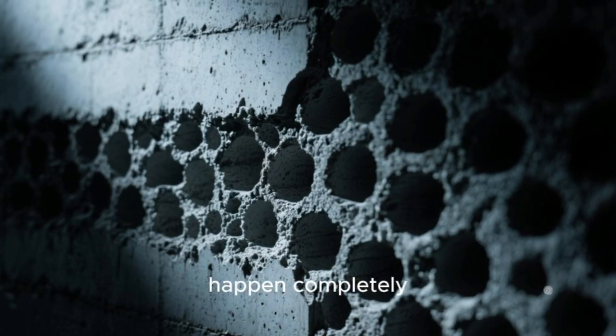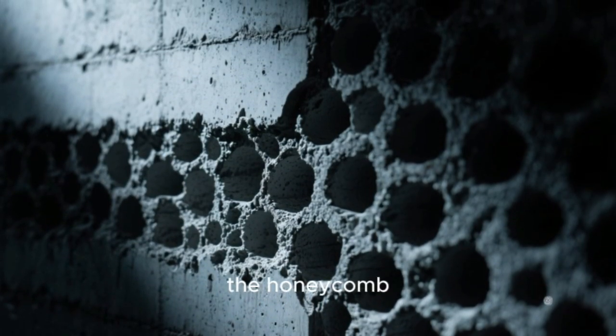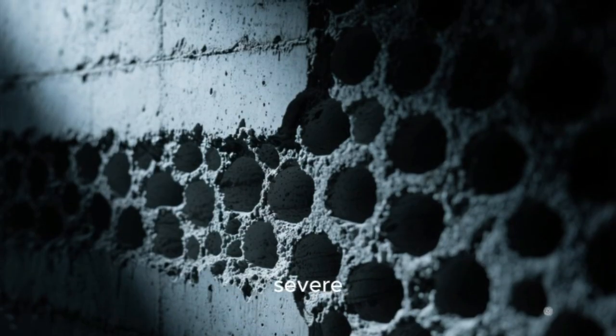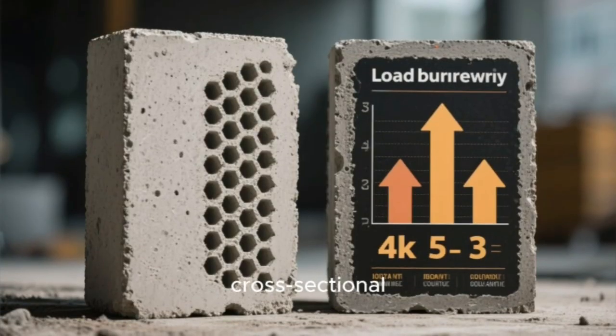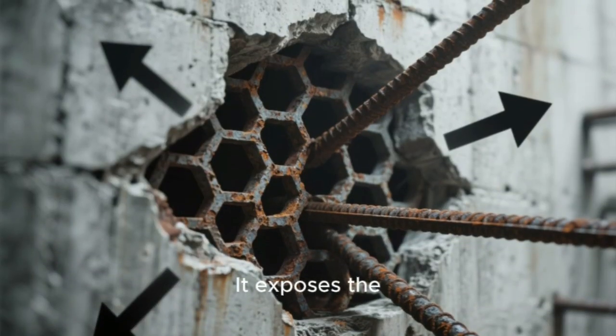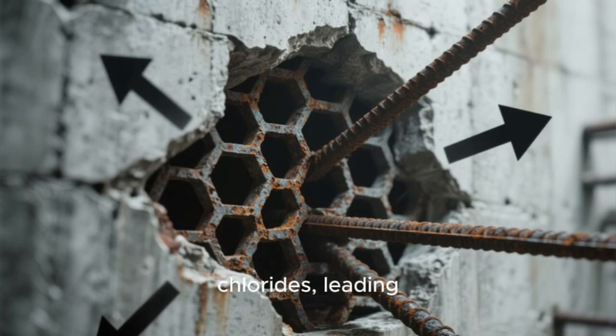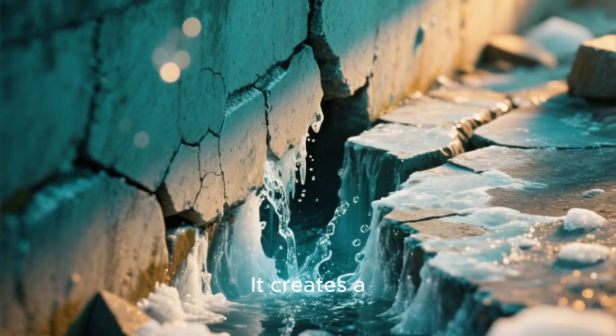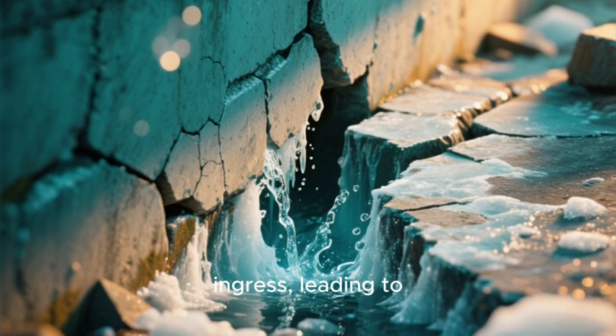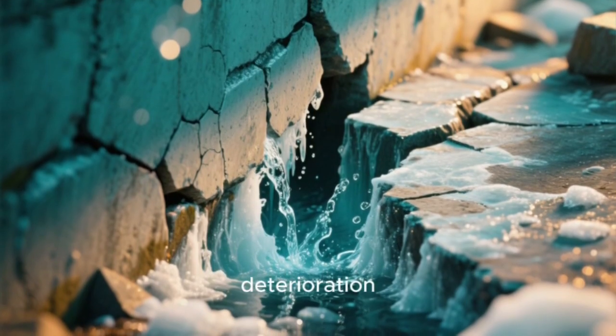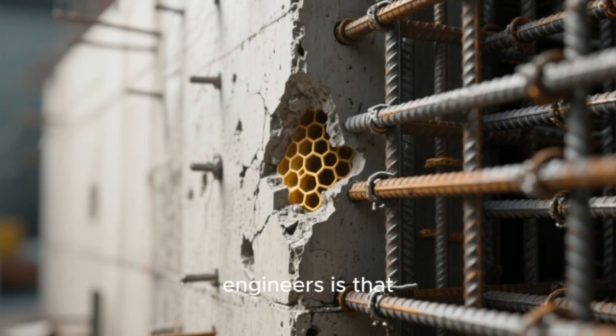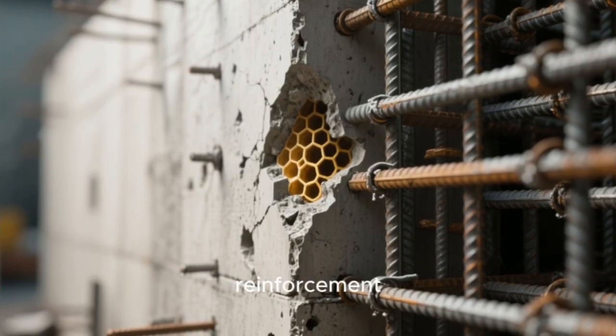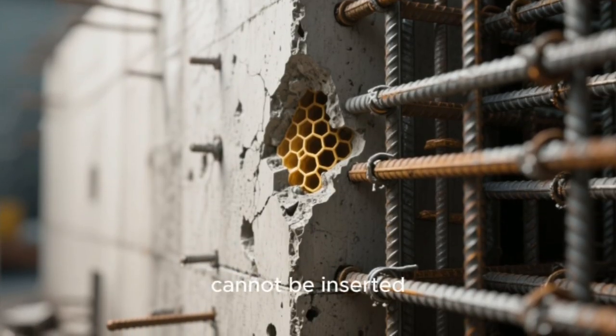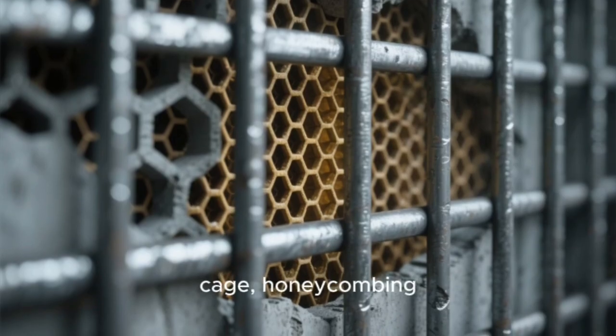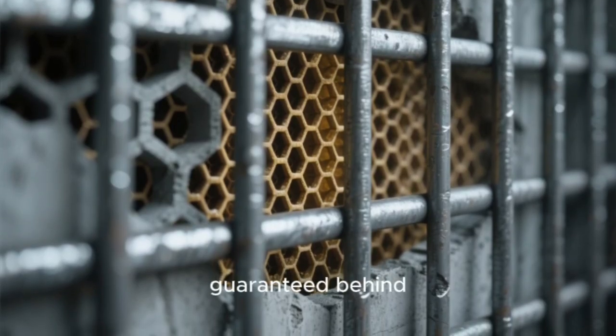When this doesn't happen completely, voids get trapped, creating the honeycomb structure, and the consequences are severe. Honeycomb concrete has a much lower load-bearing capacity. As the effective cross-sectional area is reduced, it exposes the reinforcement to air, moisture, and chlorides, leading to rapid corrosion. It creates a pathway for water ingress, leading to freeze-thaw damage and further deterioration. A pro tip from site engineers is that honeycombing often occurs in congested reinforcement zones if the vibrator head cannot be inserted and moved freely through the rebar cage. Honeycombing is almost guaranteed behind the bars.